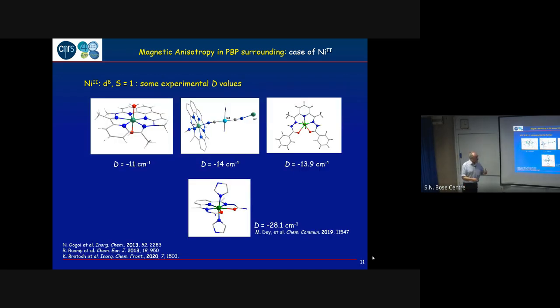And this is true for the different ligands. I just take here a few examples to show you that you can change the ligands or atoms in the apical position. You see that the zero field splitting parameter is not changing. Today, the largest that has been reported for such a system is -28. That can be explained because of the energy diagram of the d orbitals. I will come back to that a little bit later.